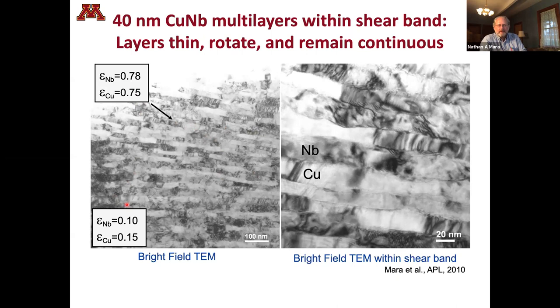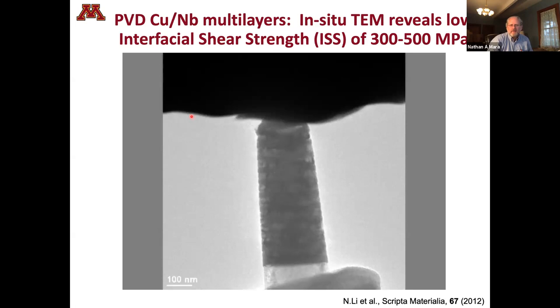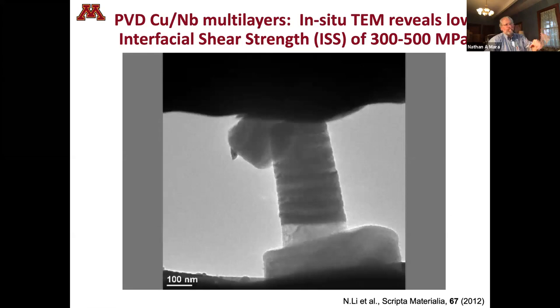Well, what we found in this work was that once these layers have rotated into an orientation where there is a resolved shear stress on that interface, they start to slide, and they slide really, really easily. How did we find this out? Well, we stuck it into the TEM again. We made a little pillar, and then we put this at a certain orientation where now we will apply a shear stress on this pillar. So you can see our individual layers here. When we do that, you see it slide like a deck of cards, just right at that interface. And so we found that the interfacial shear strength of this material is extremely low.